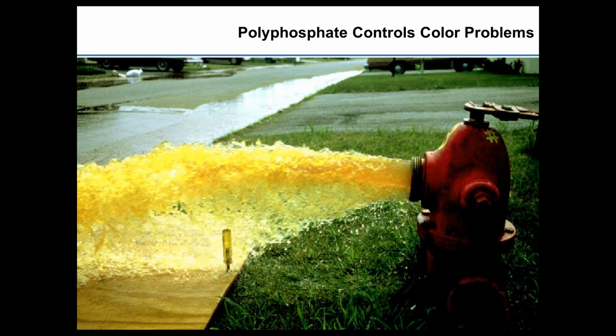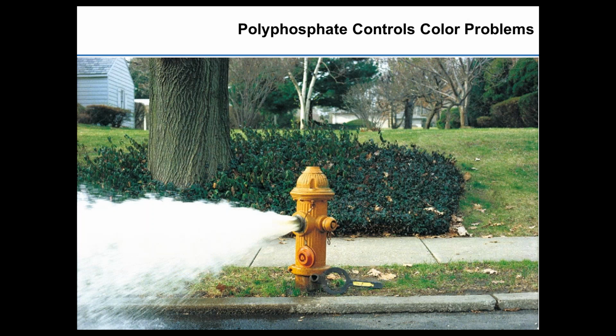The faster that water clears up, the cleaner your water is and the less tuberculation and scale you have in the distribution system. Ideally, when you flush a fire hydrant, it flushes dirty for a few seconds, and that's mainly because of the water trapped between the distribution main and the fire hydrant itself. So you will always see at least a little bit of dirty water when you first open a hydrant. As the water switches to water that's in the distribution main, it should clear up relatively quickly unless you have a lot of scale and tuberculation.